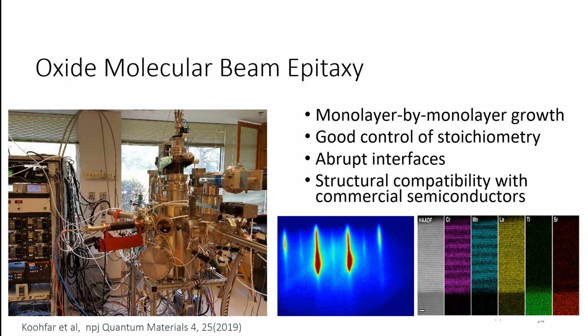So in this stack here, I'm showing you a high-resolution electron microscope image taken with some of the TEMs that are located here in Bill Center, where each of these dots represents a column of atoms. So you can see that these films are really, really highly ordered. The contrast you see here is when you go from the substrate to the film. And in the film, we can use the techniques in these electron microscopes, which also allow us to have more element specificity, where we can very precisely see that here we're growing exactly 2 chromium layers, and here we have exactly 1, 2, 3 layers of these manganese containing compound.